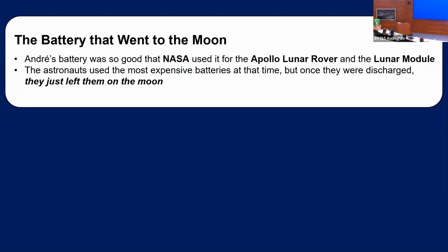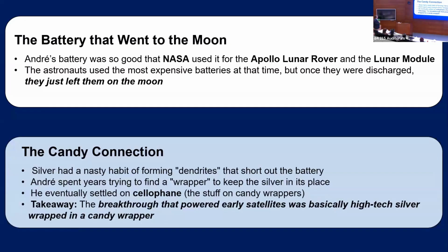So this battery actually was used in space. They took it to the moon on the Apollo lunar rover and the lunar module. But because it cannot be recharged, when they were completely discharged, they just left them as trash on the moon. They're still there. Another trivia there is the candy connection. Silver, because it's a soft metal, tends to form what are called dendrites, protrusions that, under electric current, come out of the silver anode, and they can short the battery. So he spent a lot of time trying to find a way to suppress those, and he found that a coating of cellophane, which is what we use to wrap candy, was effective at reducing these dendrites. So basically, these batteries were wrapped in candy wrapper.